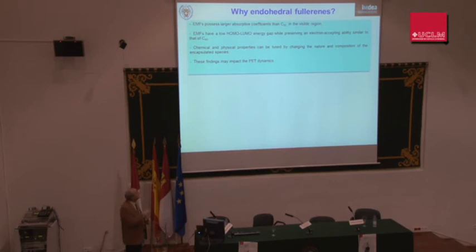Okay, why use endohedral fullerenes? Because, well, there are many advantages. The first one is they possess better absorption coefficients than pristine C60 or C70. So that is a very good improvement. In addition, you have a very good control on the HOMO-LUMO level, simply because you can modify the species incarcerated in the carbon cage. And also, as I mentioned, these findings could impact the photoinduced electron transfer processes.